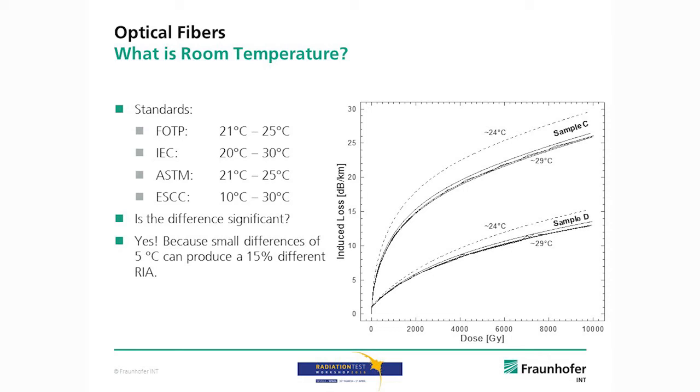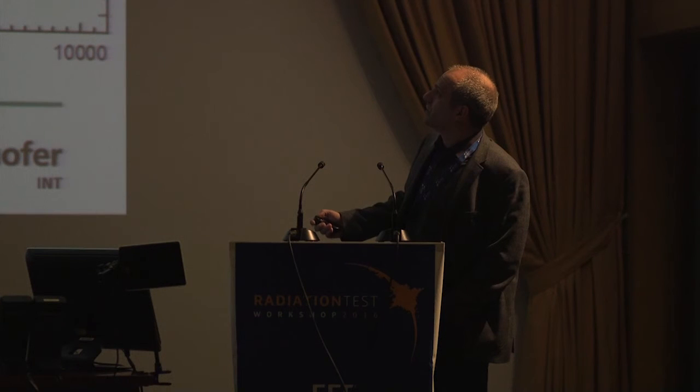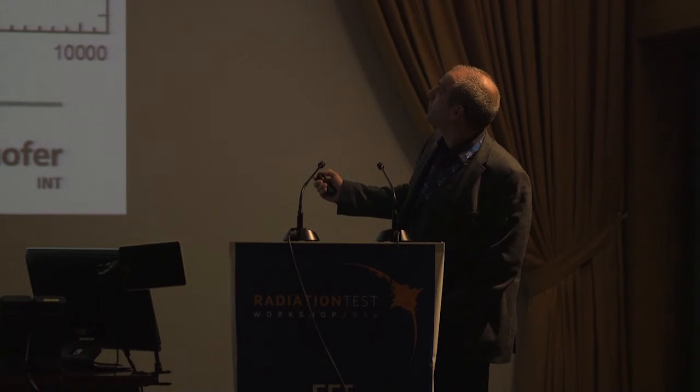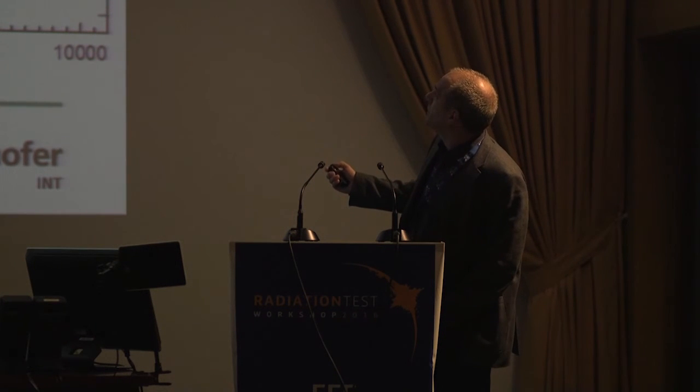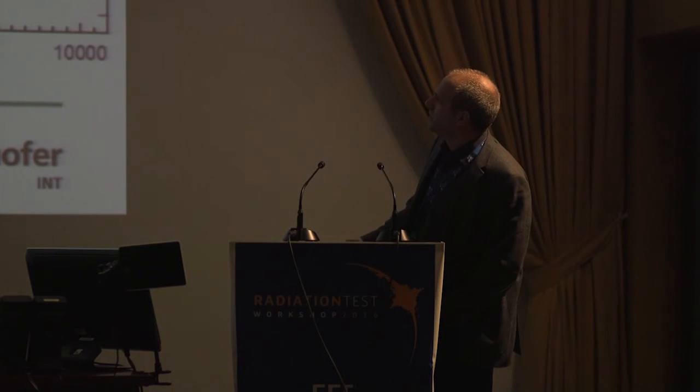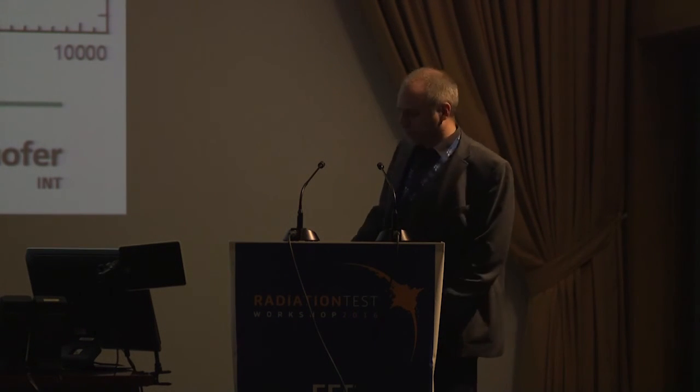But I wouldn't ask this question if there weren't a problem with it, because these are wide ranges, like a 10 degree range here, and we did some measurements of exactly the same fibers with the same setup, at 29 degrees and 24 degrees. It's a 5 degree centigrade difference within this window, and it has about a 15% difference in the result.